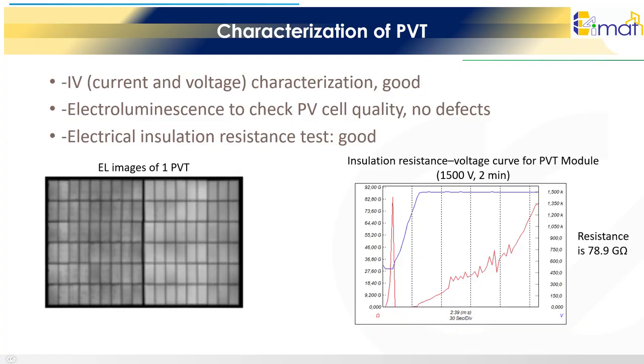After production of the PVT, several characterizations have been performed. Due to the simplified design of the heat exchanger, PV module electrical properties have been characterized before the gluing process. The application of glue and heat exchanger does not impact the insulation properties of the PV module. The current and voltage measurements of produced PVT modules showed no deviations from expected and predefined values. The electroluminescence procedure for PVTs confirmed the reliability of previous measurements and showed no electrical failures. Insulation resistance test showed good results as well, which fulfills the insulation resistance requirement according to the standard.